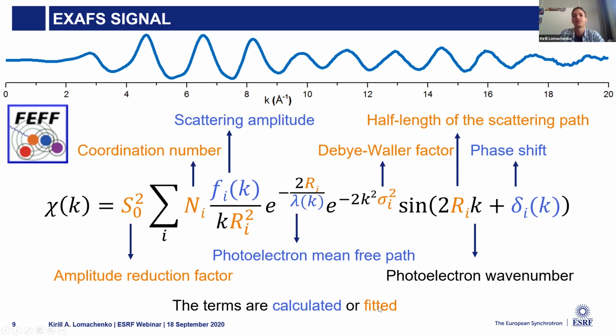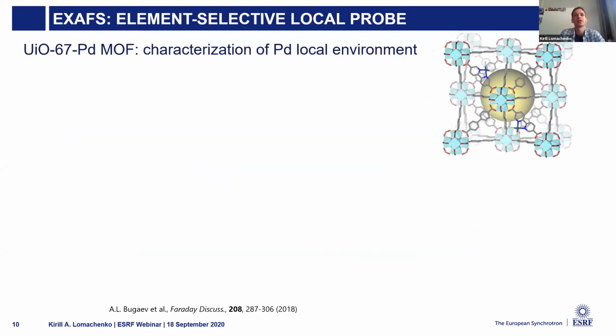By doing EXAFS fitting and minimizing the discrepancy between the fitted curve and the experiment, we can find the values of these parameters that correspond to our material. A simple illustration of this is...